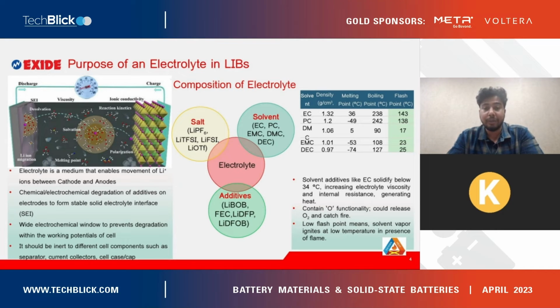And for solvents, commercially we use EC, PC, DMC, DEC, and you can see this table where you can see their physical properties. Basically, that is responsible for the lithium ion conduction and the flash point. Particularly, I would say some of the electrolytes have EMC composite, and EMC is basically added for low temperature performance because of its low viscosity. But you can see its flash point is very low, which means that in presence of fire, it can catch fire. It takes a flame.